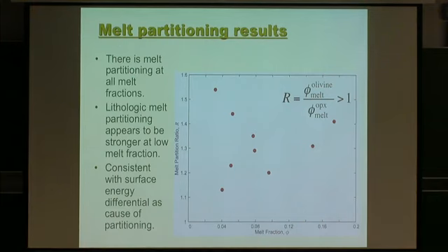So we see this is quite consistent, and then this is what you plot, having all these thousands of grains and then doing the averaging. This is the ratio between the melt associated with olivine divided by the melt associated with OPX, and you see most of them are always above 1, so more melt is associated with olivine than OPX. Granted, there are quite a bit of fluctuations from those rocks, because these are each individual grains and then you do the average.